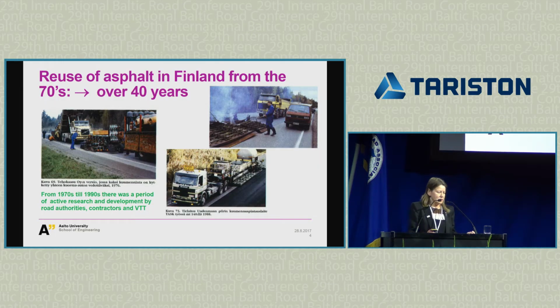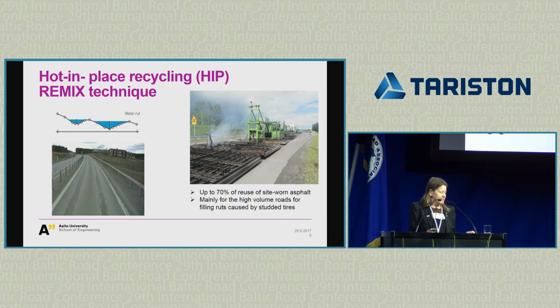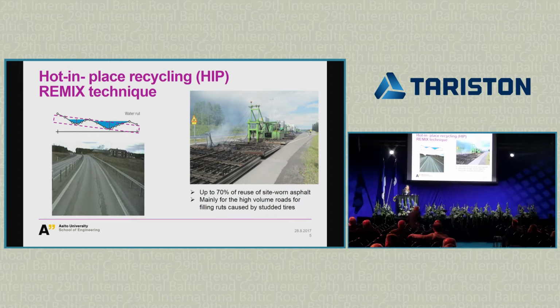So we've been doing this over 40 years in Finland, and this hot-in-place recycling is really the working horse for the high-volume roads when we need to fill the ruts that come from the studded tires. And the beauty of this is that we can use 70%, give or take, the old material. We can retain the hard aggregate we've invested for these surface mixes. And the cost is, depending on how much admixture, new material you add, somewhere around half the normal asphalt slab.